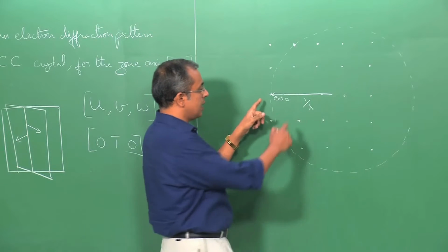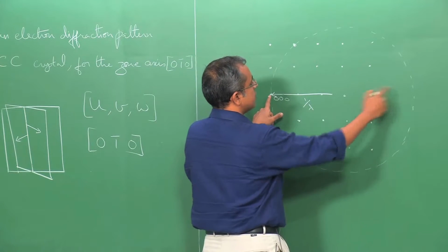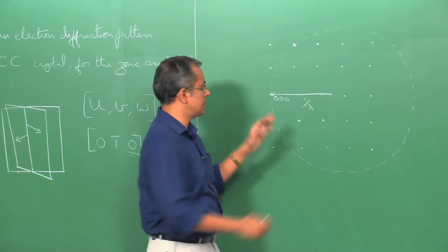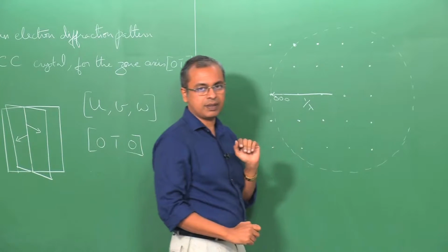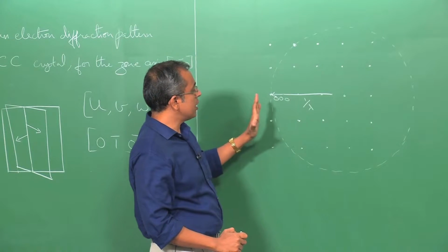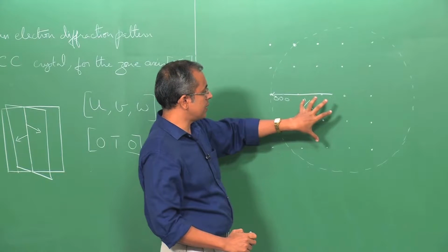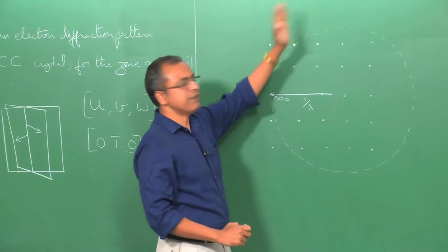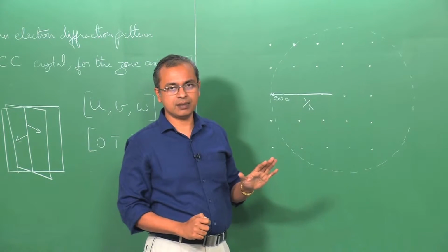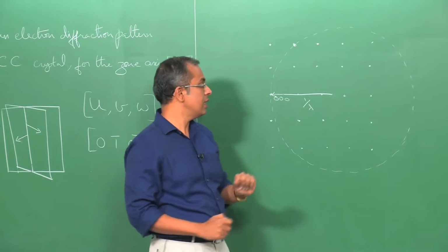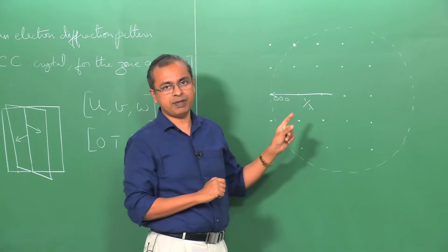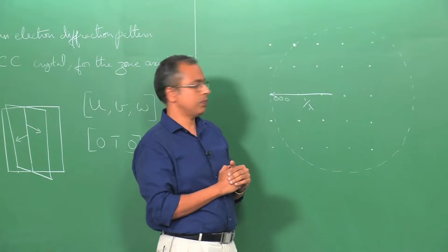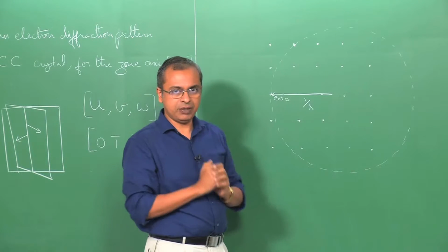Okay. So, therefore, you can actually independently vary the radius of this circle, or the radius of the sphere, in this case a circle appearing as a circle in 2 dimensions. You can independently vary this sphere, and therefore, for a given combination of crystal and wavelength of radiation incident on it, a specific set of points would satisfy the Bragg condition, the diffraction condition, right. So, that set of points is going to vary as you change the wavelength. It is not the same regardless of the wavelength. So, that is one point that we need to keep in mind.